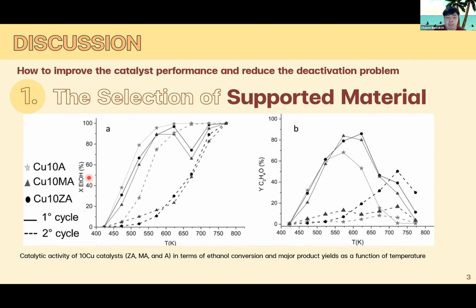The copper alumina, denoted by the star symbol, shows the best performance of ethanol conversion when we operate at high temperature. But when we see the result of the yield of acetaldehyde, the yield of the copper alumina is the lowest when we compare with the other catalysts. And moreover, in the second cycle, the copper alumina has poor performance in the yield of acetaldehyde. On the other hand, the copper zinc aluminate, denoted by the circle symbol, shows the best yield of acetaldehyde when we operate in the second cycle, and the result is similar to the first cycle. Even though the copper zinc aluminate is slightly lower than the copper alumina in terms of ethanol conversion.